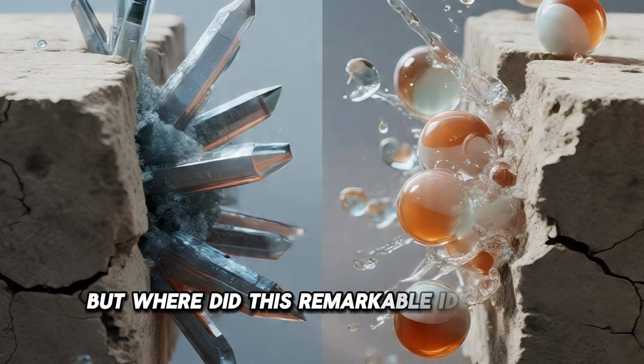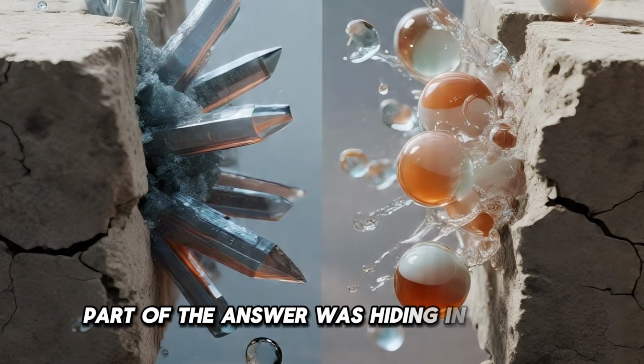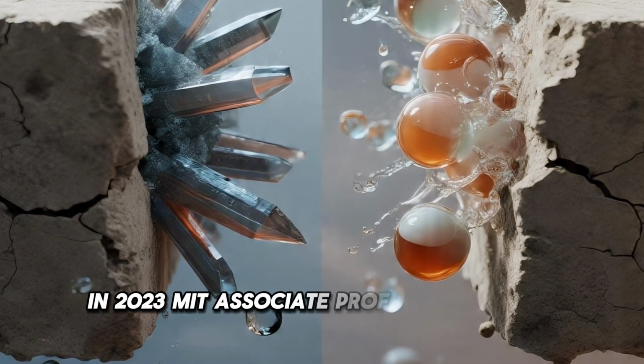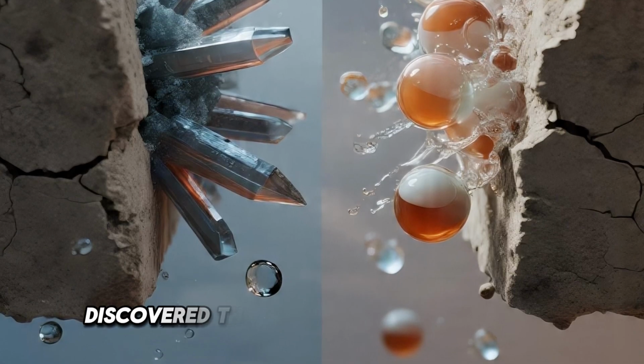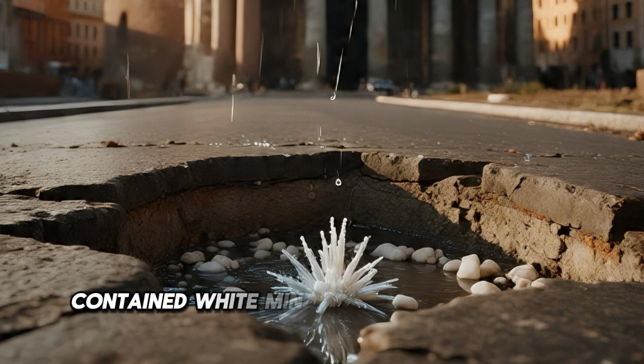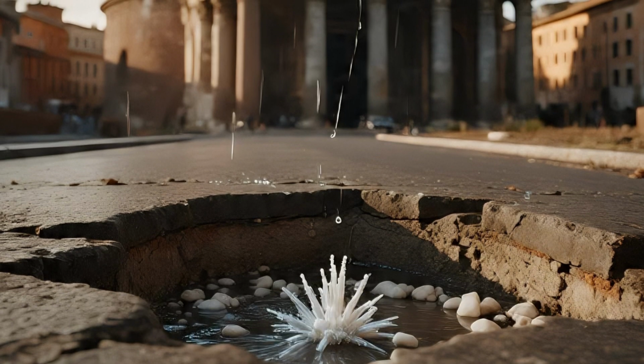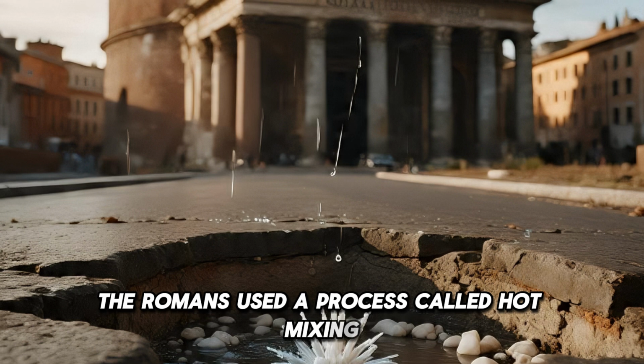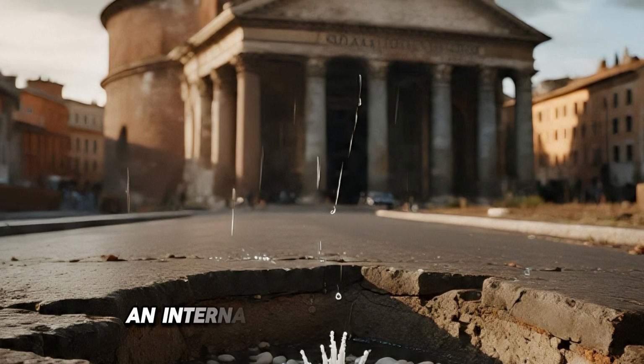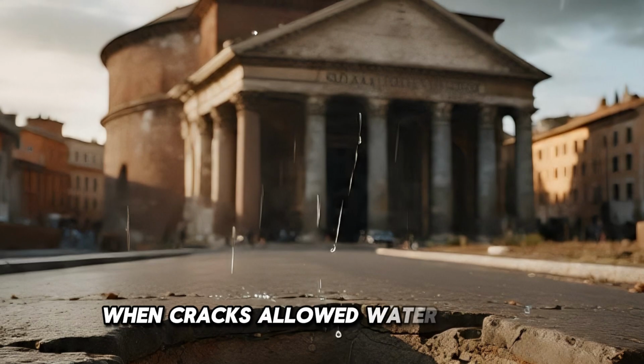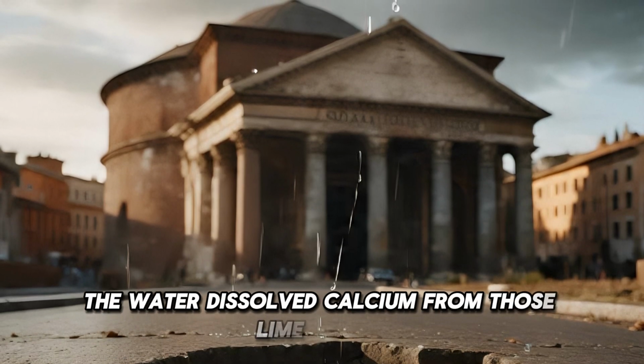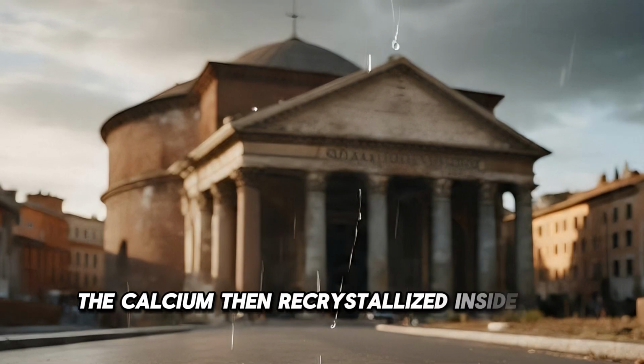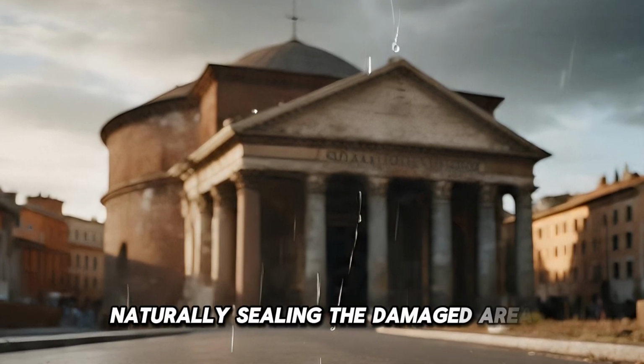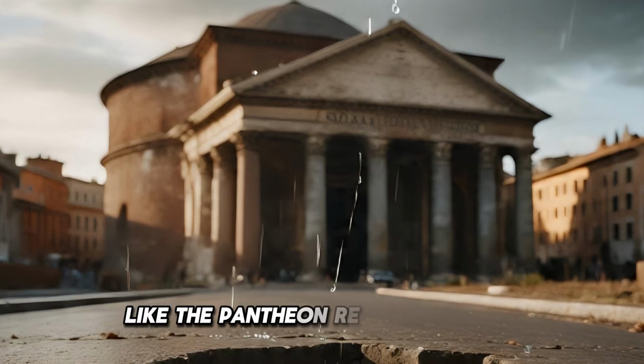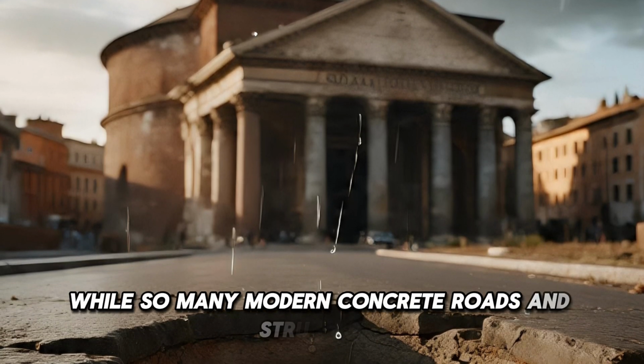But where did this remarkable idea come from? Part of the answer was hiding in history. In 2023, MIT Associate Professor Admir Masic discovered that ancient Roman concrete contained white mineral inclusions known as lime clasts. The Romans used a process called hot mixing with quicklime, giving their concrete an internal self-repair mechanism. When cracks allowed water to enter, the water dissolved calcium from those lime clasts. The calcium then recrystallized inside the fracture, naturally sealing the damaged area. That helps explain why structures like the Pantheon remain standing, while so many modern concrete roads and structures seem to crumble before our eyes. Now let's talk about money.